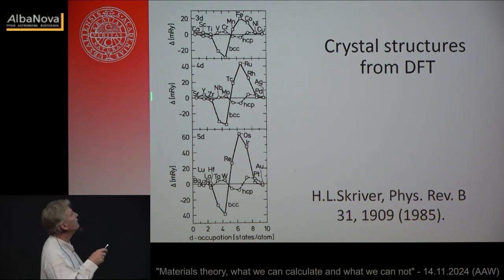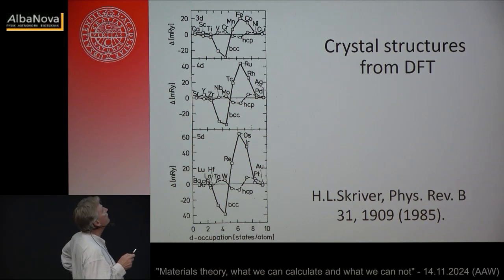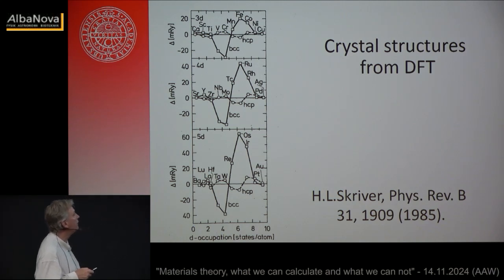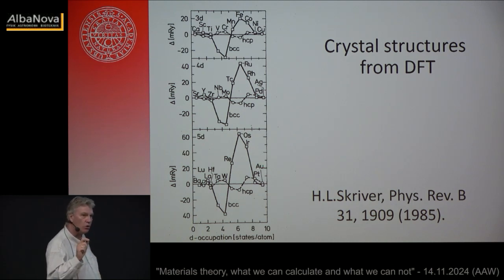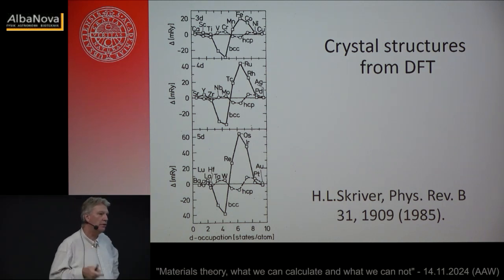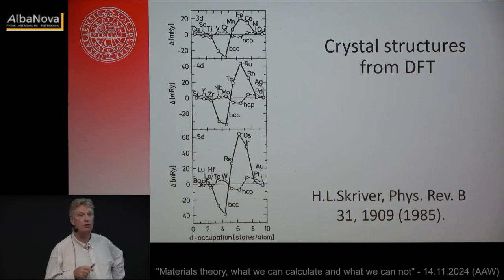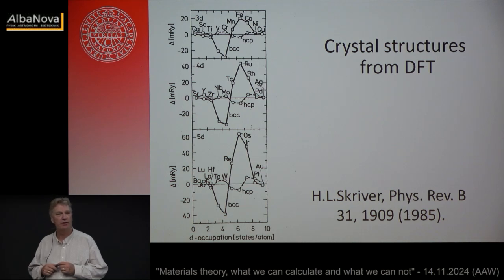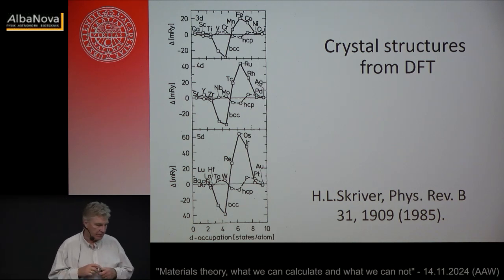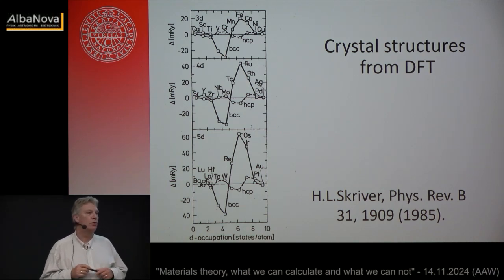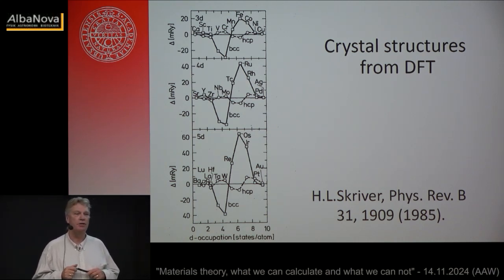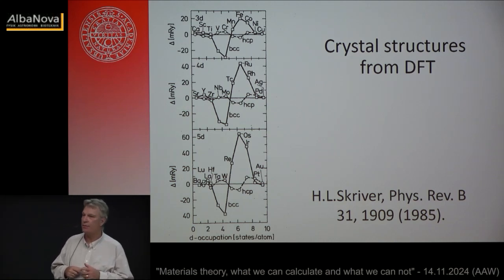And so this graph shows, I took this from his paper, it's for the 3D, 4D, and the 5D transition elements, and everything works out well except gold here. And then with a small fine adjustment to the accuracy of these calculations, it was shown by us and others that gold also comes out to be FCC. So structural properties are fantastically well reproduced in this theory. And so we were very much interested in this in the 90s. We did a lot of calculations to support the high pressure community that really are looking at crystal structure stability as a function of applied pressure, often in diamond anvil cell techniques and those kind of experiments.